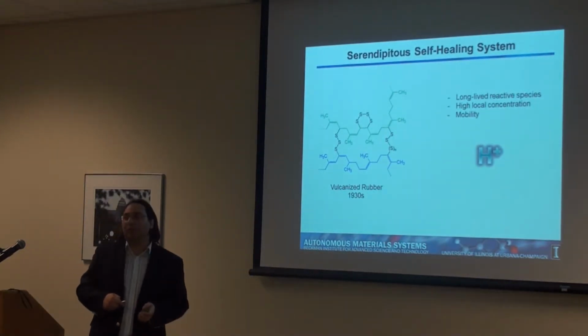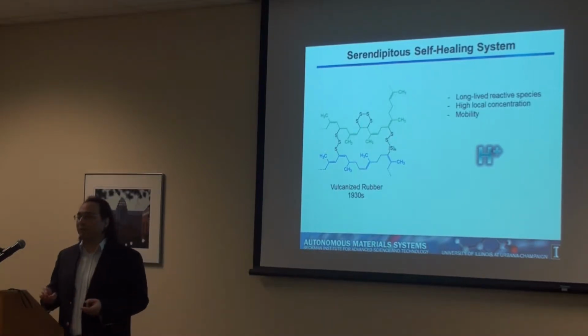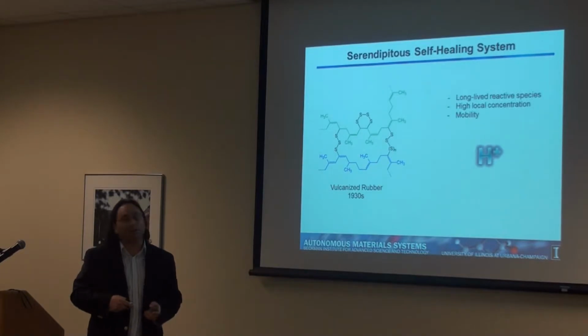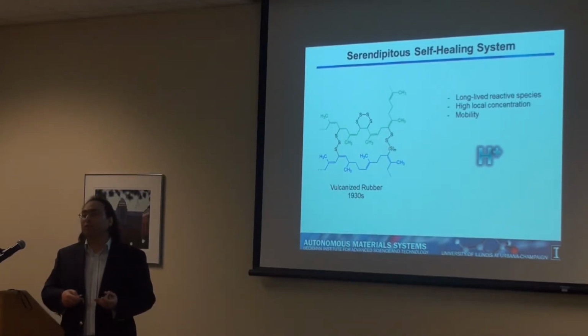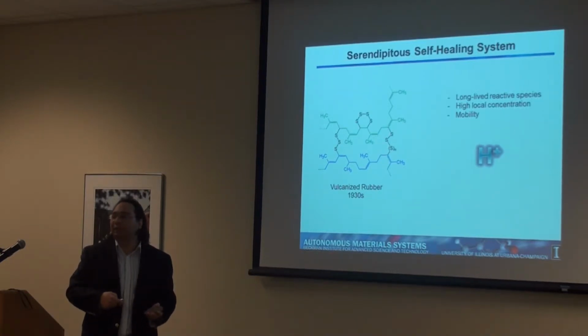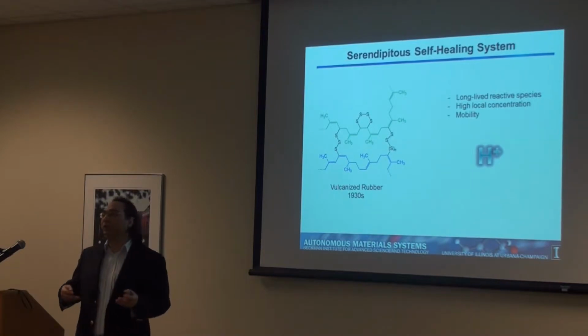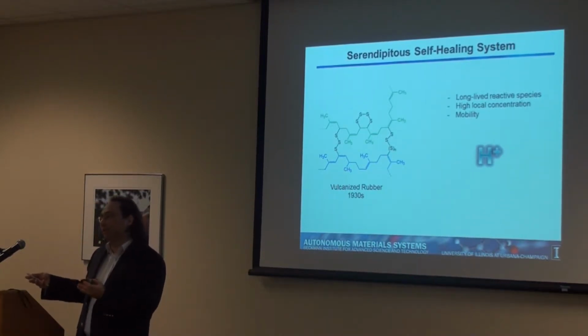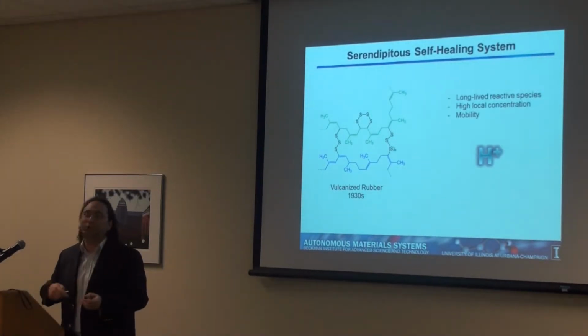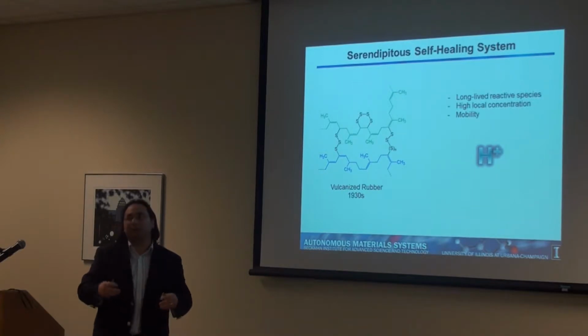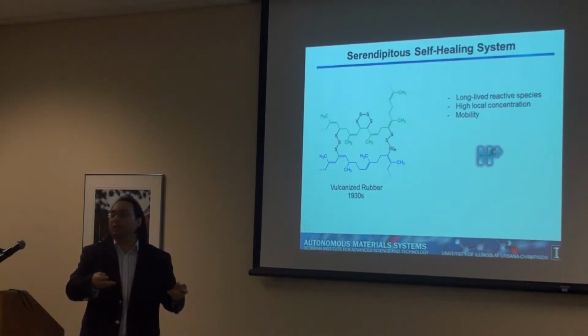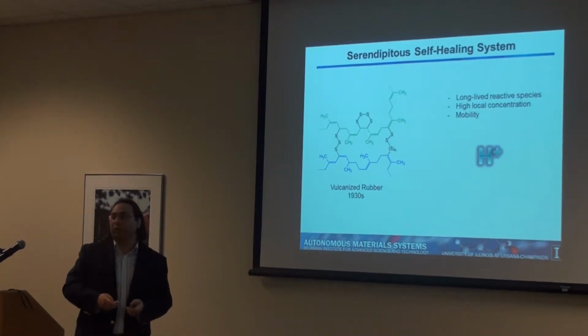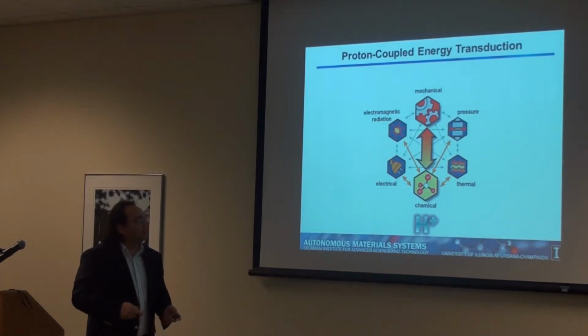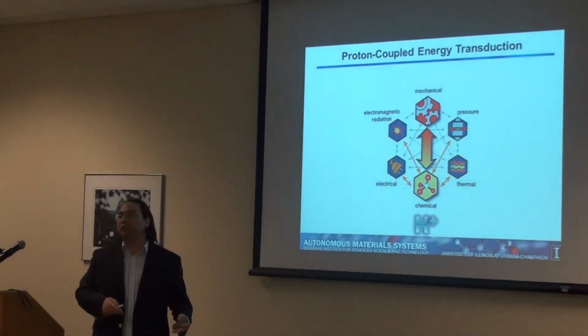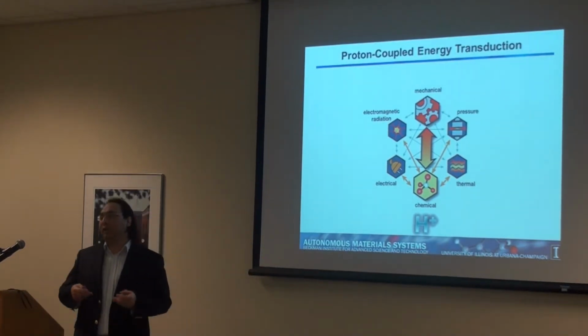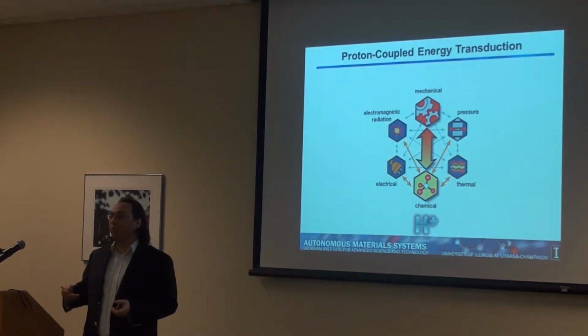Now, local concentration can be a problem, so we can produce a lot of acid by having, for example, an acid amplifier. But in this case, the acid is not our reagent. The acid is a catalyst. So I don't need to produce too much acid. What I need is between 5 and 20% of a co-monomer that is sensitive to acid and will undergo some acid-catalyzed reaction. So I can produce a very small quantity of a catalyst that will induce a high quantity of reaction. And maybe this will give the features that we want. Obviously we don't want the acid there all the time, so I'm not going to add acid to my polymer. I need to add the feature that when I apply mechanical force, I will produce an acid.